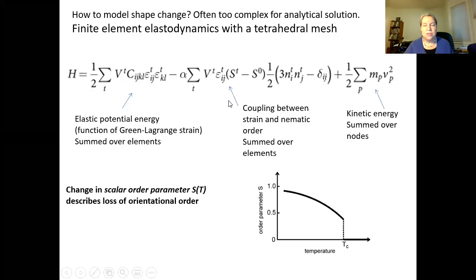Now I need 2 more terms in my energy. So one of them is a coupling between strain and nematic order. So epsilon ij is a mechanical strain. And then this S is something about the nematic order parameter, and it gets bigger or smaller depending on whether the material is hot or cold. And so when it's hot, the scalar order parameter drops, and when it's cold, the scalar order parameter is larger. That can be a local variable because, for instance, the material might not be uniform in temperature, or it might change with light exposure. And then this is just the Q_ij matrix.